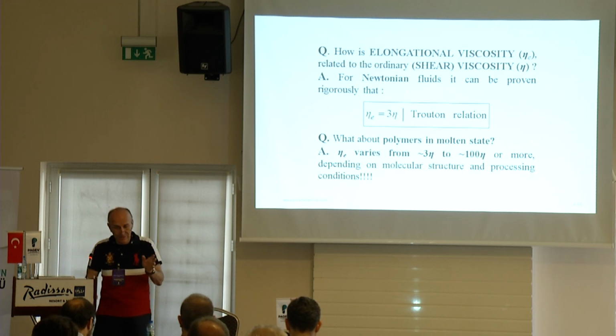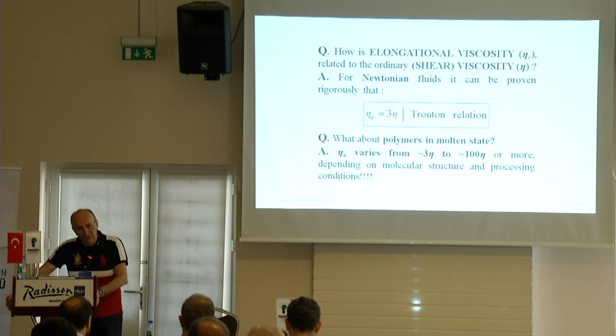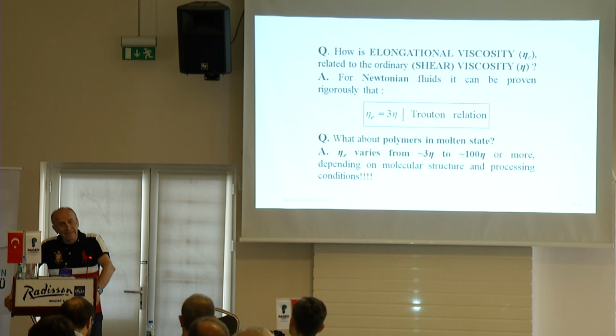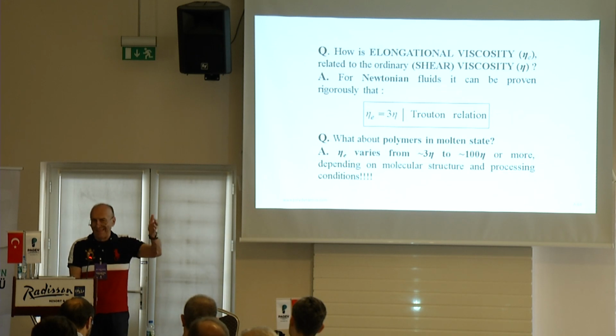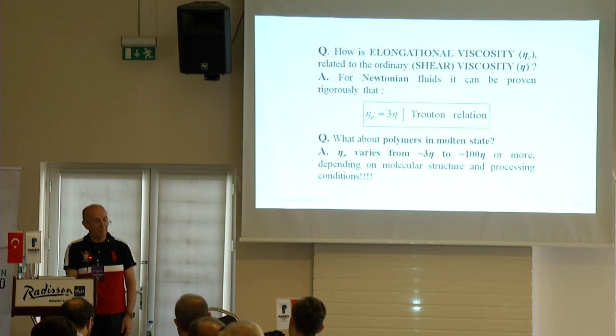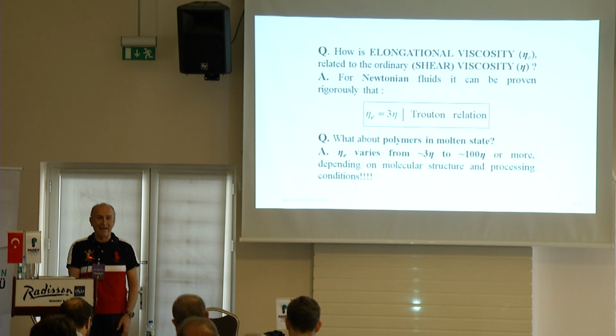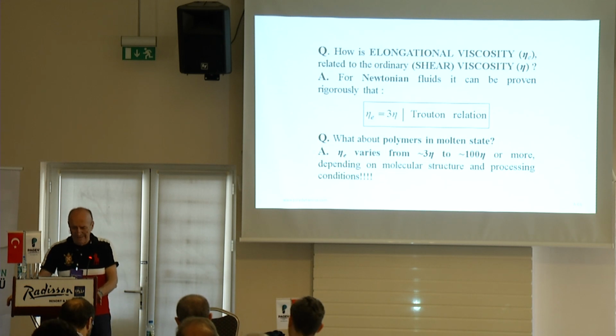But for polymers, under usual processing conditions, it will go perhaps up to 100. And for some solutions, it may go to 1,000. I've seen measurements up to 15,000 for the ratio for solutions. For molten polymers, the ratio is perhaps up to about 100.